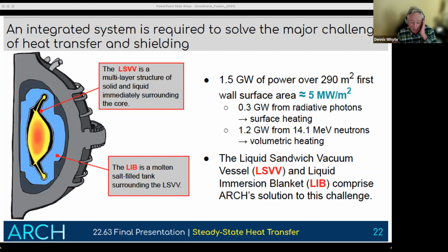Actually, there's a third reason, which has to do with the special needs for recovering the fuel. The tritium fuel is very dilute in the molten salt. So the other reason to control the chemistry, or the purity, is that the redox potential of the salt is necessary for controlling the form of the tritium that is there and your effectiveness in recovering it. So that becomes a physical chemistry challenge, which we're starting a project on as well.